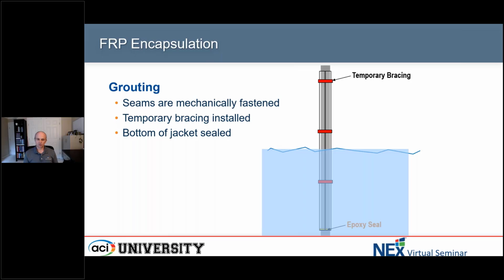There's also, of course, some type of seal that we need to use, especially on the bottom of this encapsulation, so the grout doesn't flow out through the bottom of the member that we're trying to encapsulate. So there's usually some type of seal, usually with an adhesive like an epoxy or some type of foam seal that's used at the bottom of the encapsulation to seal it off.